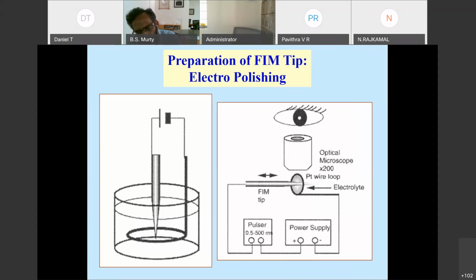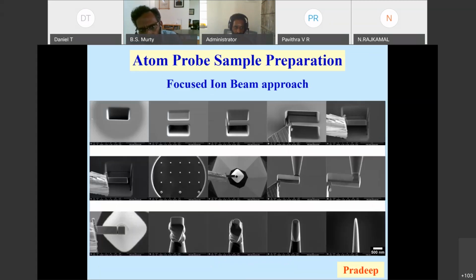Long back, when I started my life with atom probe tomography, this was around 1999 to 2001. For 2 years, I worked on atom probe, and that was the time we used to use a technique called electropolishing technique, where you take a sample in the form of a needle or a ribbon, and using an electrolyte, you sharpen the needle, and then you will put it into a TEM to ensure that the needle is very sharp before you put it into atom probe and use it. And whereas now we have techniques such as focused ion beam that has come into picture.